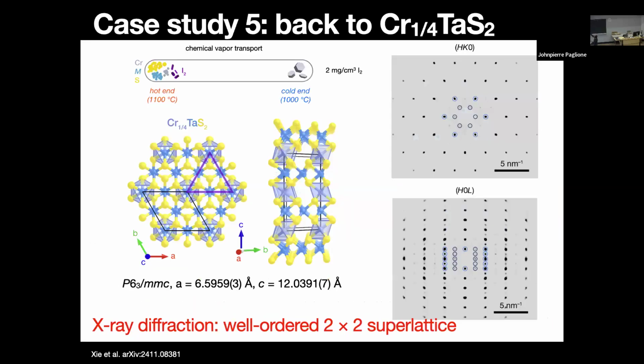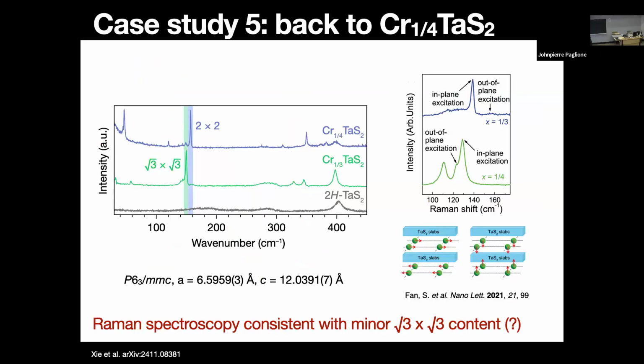So we had made this material, the non-collinear AFM. By X-ray diffraction, it was a well-ordered 2x2. We saw no evidence in X-ray diffraction of any root 3x3 in any of the frames. We go frame by frame. All the superlattices we see are 2x2. When we look in the Raman, we see the phonon modes associated with the 2x2. And we see some other modes that look eerily similar to what you might expect for the root 3x3, but other people have assigned those to out-of-plane versus in-plane vibrations.